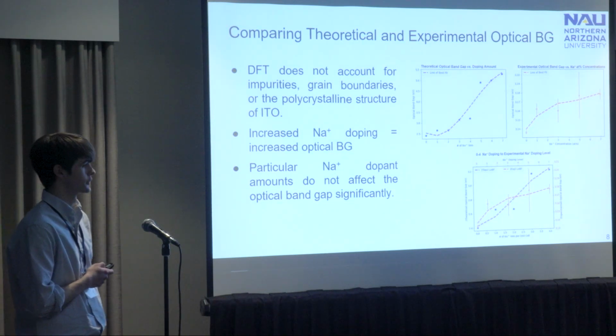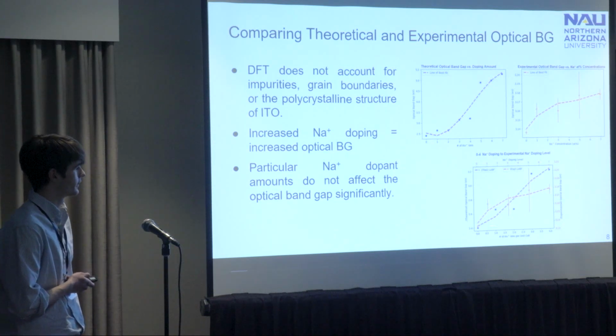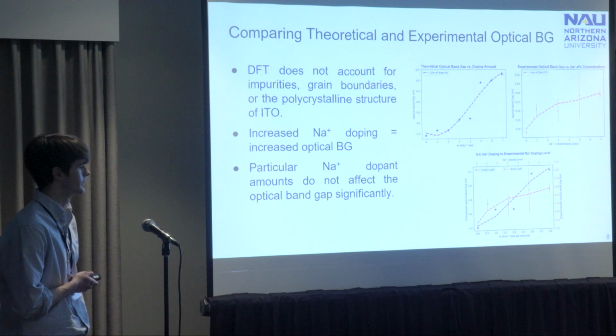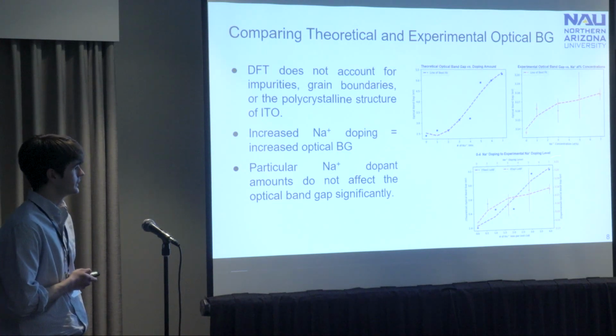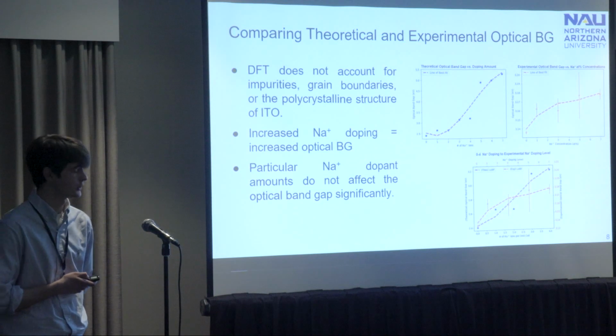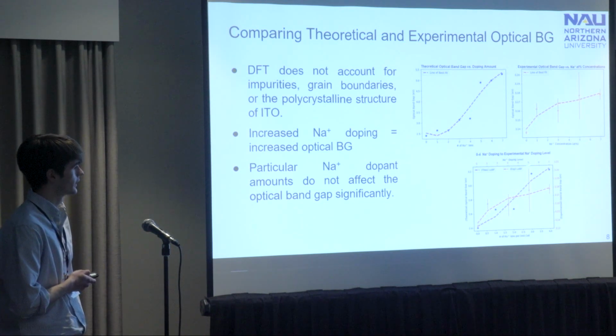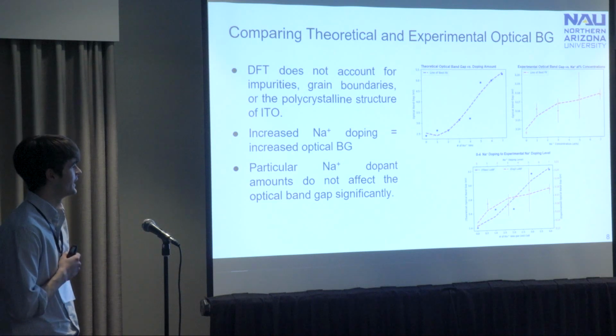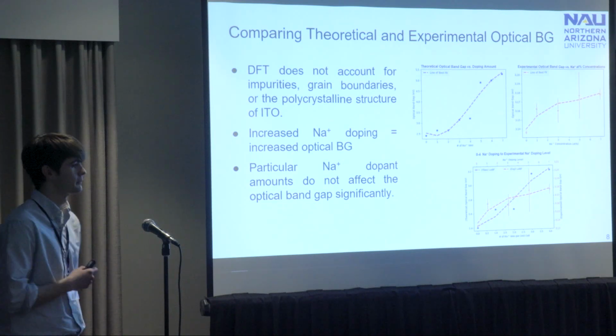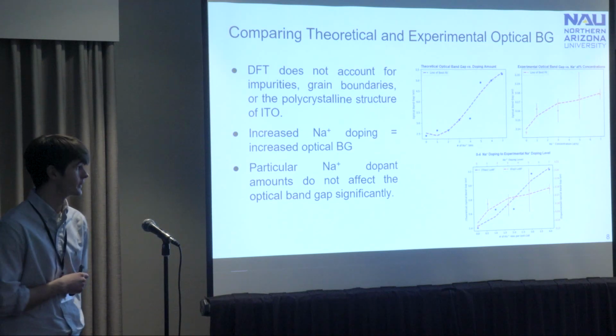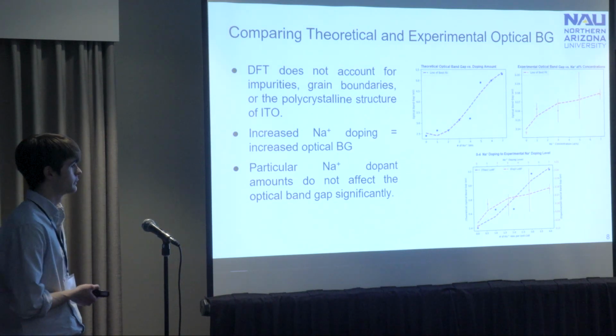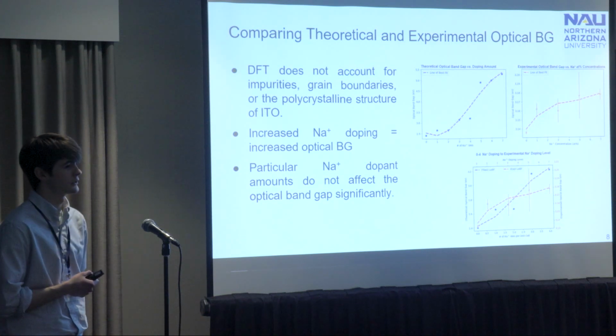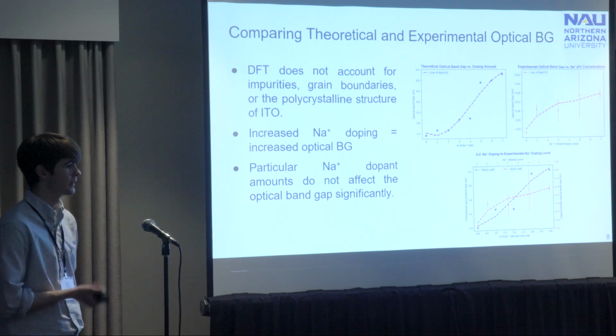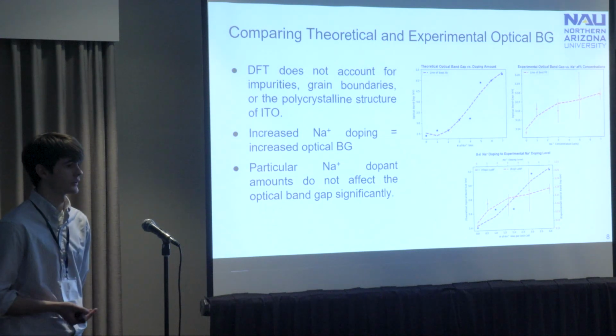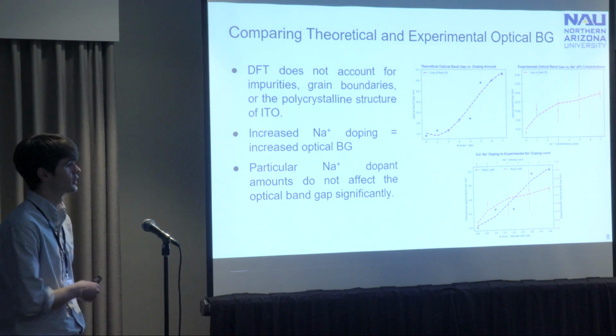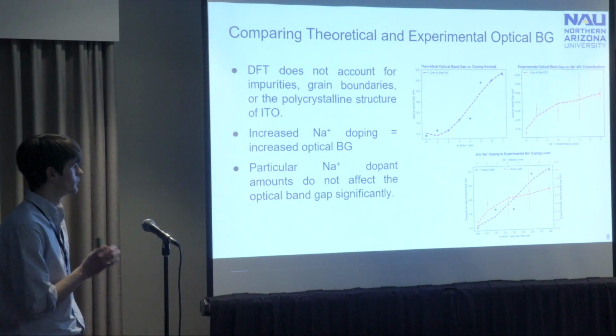And so if we were to take those 2.4 sodium ions we found earlier and use this graph, where the bottom blue x-axis corresponds to sodium ions in a unit cell and the top is sodium ion atom percent in an ITO solution, that would be around 3.5 to 4 sodium ion atom percent per ITO solution being the most optimal sodium ion doping concentration. What's really cool about this is that experimentally we found the 3 sodium ion atom percent ITO solutions in thin films to perform the best in balancing transparency and conductivity at the same time. But this data suggests that we can push that boundary a bit further to around 4 sodium ion atom percent.